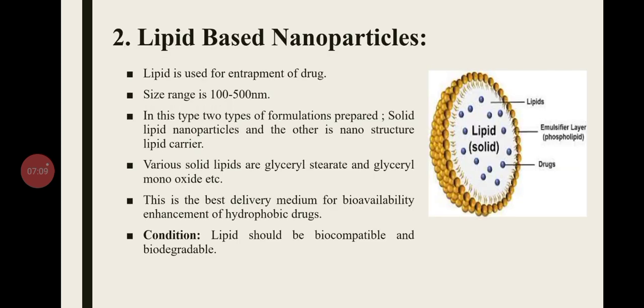The next category is lipid based nanoparticles. So basically in this case the lipid is used for the entrapment of the drug. Their size range is 100 to 500 nanometers, and in this type there are two types of formulation we prepare. The first is solid lipid nanoparticles and the other is the nanostructured lipid carrier. The various solid lipids are glyceryl stearate and glyceryl monooleate. So this is the best delivery medium for the bioavailability enhancement of hydrophobic drugs. They also have the same condition, like the lipid should be biocompatible and it should be biodegradable.